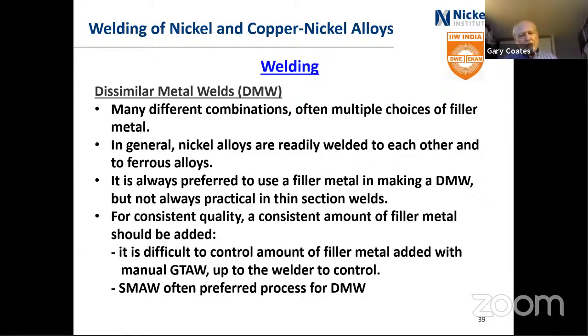And you really do want to use a filler metal there, because the weld is a combination of part of each of the base materials, maybe 15% of each, and then the rest is the filler metal composition. And for consistent quality, you do want to add a consistent amount of filler metal. So that's a welder skill that he has to learn, but it also involves doing the setup, the joint prep, and that sort of thing, so that it is all controlled carefully. And often shielded metal arc is the preferred process for dissimilar metal welds, only because the welder can easily control the parameters there. TIG welding, it is difficult to use that.